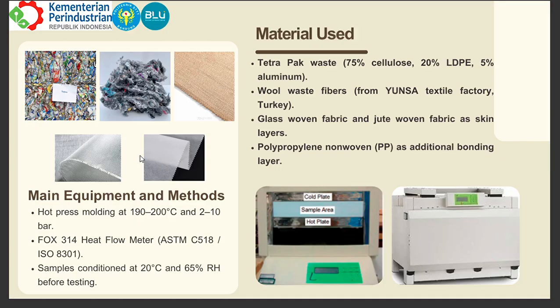This is the material they are using. The materials used include Tetra Pak waste containing approximately 75% of cellulose, 20% of low-density polyethylene or LDPE, and 5% of aluminum. The second is wool waste fibers, collected from Yunsa Textile Factory in Turkey. The third was glass woven fabric and jute woven fabric used as the outer skin layers. And the last is polypropylene non-woven, used as an additional bonding layer between the core and the skins.